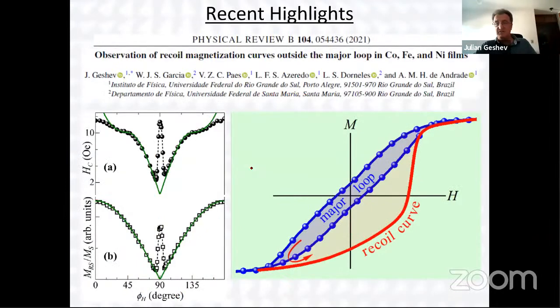And most recently, we published a paper in August, which is, I think, quite a striking phenomenon in systems that present collapsed hard axis, something like this along the hard direction. There are maxima in the coercivity and remanence coercivity and remanent magnetization. And if you measure curves close to the hard axis, for example, near the minima here, the major loop is the blue one. If you start from saturation, stop here, for example, and then go back, you have a recoil curve which is placed well outside the major hysteresis loop.